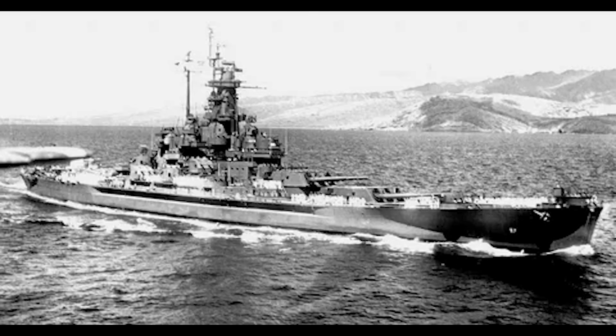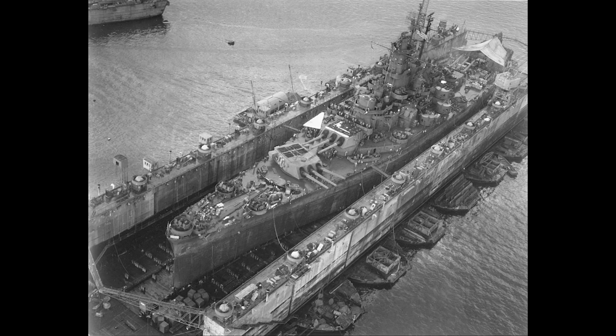USS South Dakota, the name ship of the preceding battleship class using similar armor design philosophy, took hits from Japanese 14-inch shells at the Naval Battle of Guadalcanal in November 1942. Her belt armor rejected one 14-inch armor-piercing shell, deflecting it downward without penetration, despite the shell striking at relatively close range with high remaining velocity. The barbette of Turret 3 took a direct hit that caused damage, but didn't penetrate the 17.3-inch armored cylinder. South Dakota's armor performed adequately. The ship survived the engagement, was repaired, and returned to service.